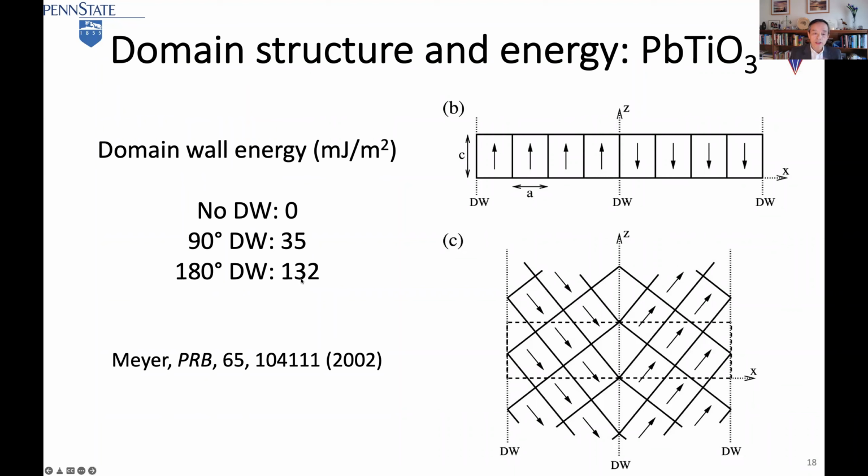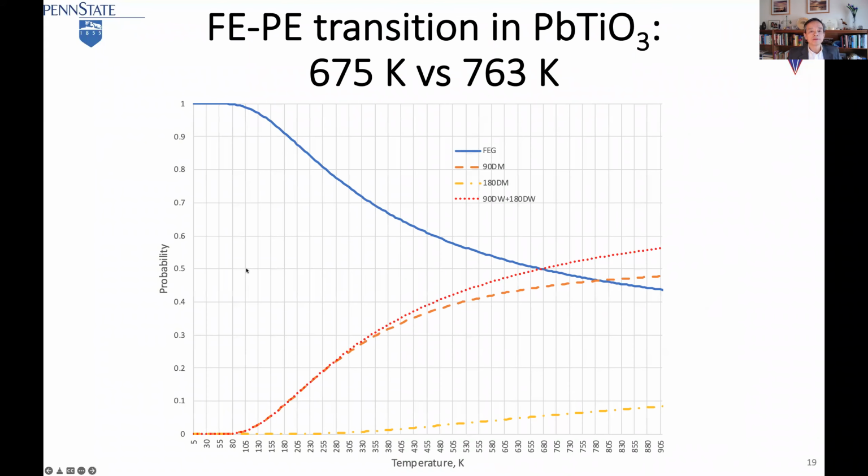And so this is the data we use. We take this data at 0 Kelvin for the time being, because there's no reporting in the literature about free energy, only 0 K energy. So we take those two data points, put them in our Zentropy theory, and then we can calculate the probability of each of the three configurations. Of course, we have to consider the multiplicity for each configuration, each microstate. So after doing that, we got our results here. These are our results.